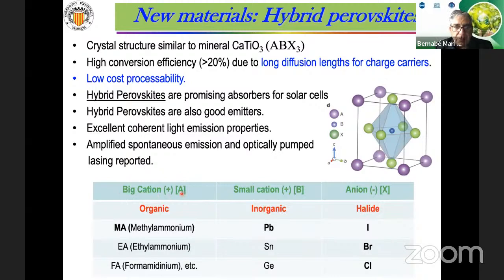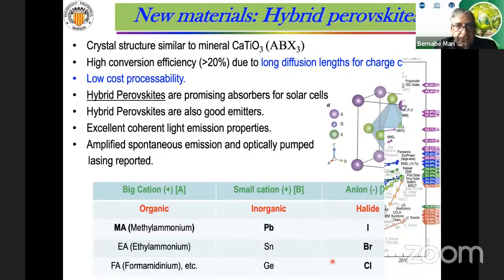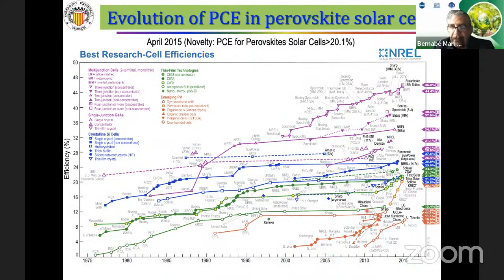We have one big cation called A. We usually use an organic one, which can be methylammonium, ethylammonium, or formamidinium. There are a lot of possibilities to use as the big cation. The structure also has a small cation. For the small cation, usually you can use lead, but also tin or germanium. And for the anion, we can use a halide: iodine, bromide, or chloride, or a combination of every material. So what happened? Here you have the novelty in 2015 for the efficiency of solar cells: the perovskite solar cell appears for the first time with an efficiency of 20%.